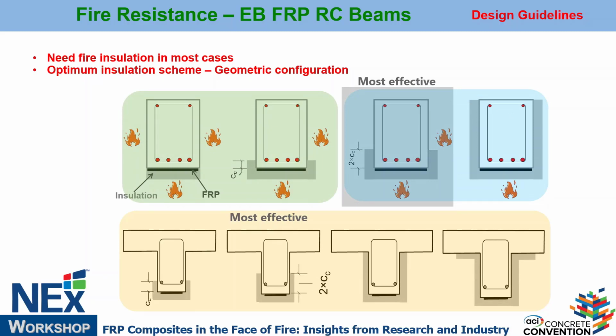So when you use externally bonded FRP, for example, just putting insulation underneath the beam is not a good option. No. You need to take it further, and even providing cover to the level of the rebars is not good. You need to take it 2 times CC, 2 times the concrete cover thickness to get the full benefit. Or you can take it fully, but you are wasting your time. You don't have to worry about that. You are wasting material and stuff. So 2 times the concrete cover thickness is the most optimum.